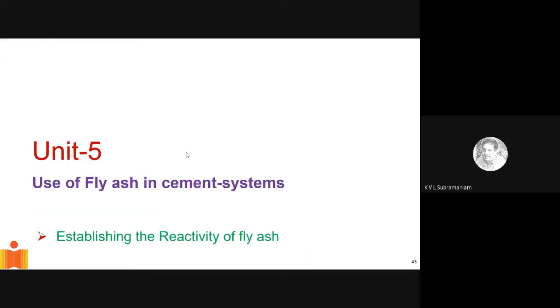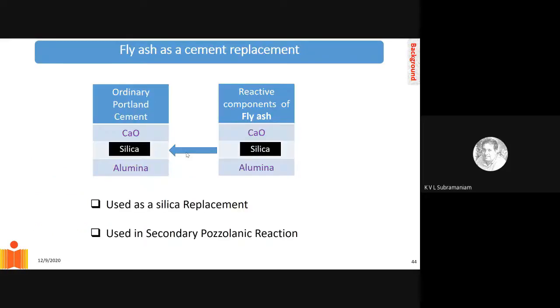Now, just to quickly show you how we optimize the use of this fly ash, which is a post-industrial waste material, in cement. How effectively can I utilize this material? If you remember the replacement strategy, and if you look at ordinary Portland cement in the table on the left, it is primarily calcium oxide, alumina, and silica. And primarily it is calcium and silica that we are interested in. And when I bring in fly ash or any other supplementary cementitious material, it comes with silica.